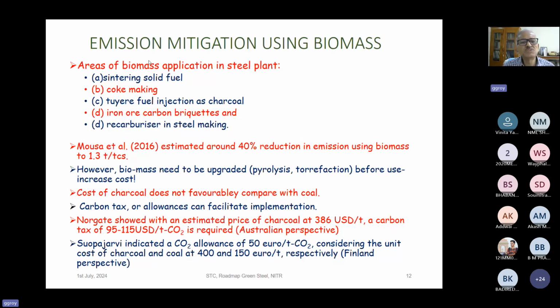Similarly, we can use it in coke making. During the blending of the different coals, we can use some amount of biomass, and then we can reduce the coke, and it is also sometimes called biocoke. And most successful is the tuyere fuel injection as charcoal. We can inject the charcoal through the blast furnace tuyere, and it has been theoretically shown that 100% replacement of the pulverized coal by the charcoal is possible, considering the heat and mass transfer in the process. And some plants have also demonstrated charcoal injection into the blast furnace.